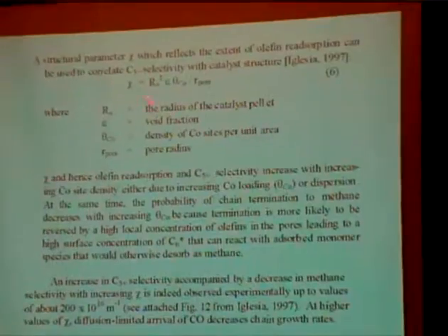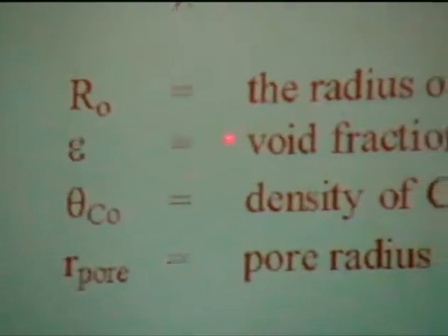Chi is a function of the radius of the catalyst pellet or thickness of the catalyst layer, the void fraction, and the density. It's directly proportional to the density of cobalt sites per unit area, and inversely proportional to the pore radius.